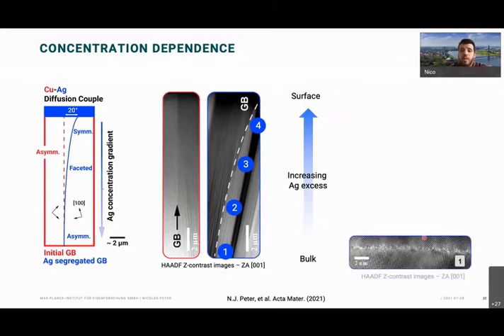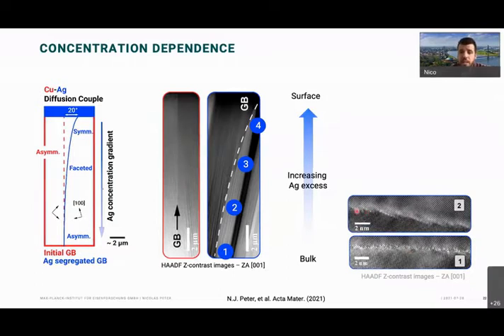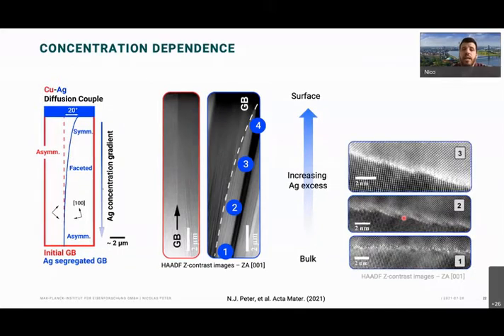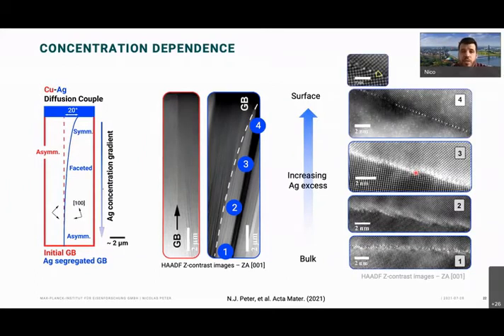So from the bulk, where we have the lowest silver, we have more or less our reference boundary with bright silver that I mentioned before, distributed along the boundary. And then eventually we start coming into the faceted state, where we form facets that are decorated with silver again. And towards the surface, one facet segment, the silver-containing one, grows in length. So it becomes longer and longer, while the other one remains more or less straight. So at the very surface, we finally find our long straight line here, which is quite interesting because then faceting is no longer observed. And this is again our 210 symmetric boundary that I have been talking about quite a lot.